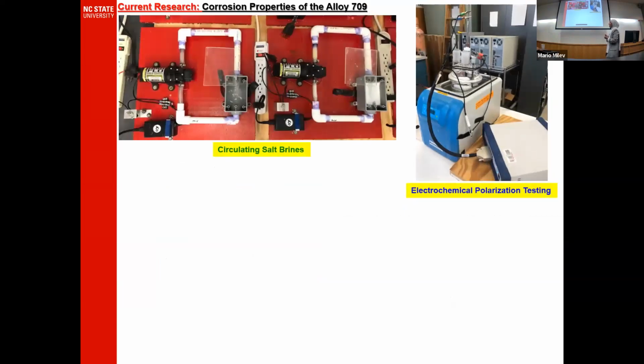For my current research, I am studying the corrosion properties of 709, because in dry casks, self-accelerated corrosion was observed, in which corrosion was found at the interface between the stainless steel canister and the nuclear waste. So it's important to study the behavior of 709 under corrosion tests.